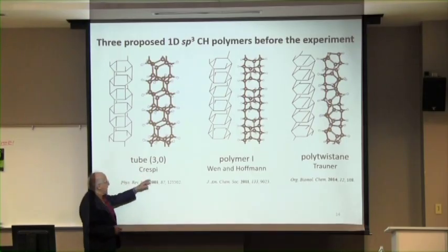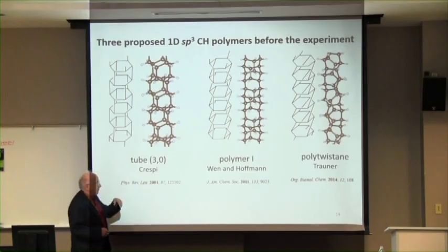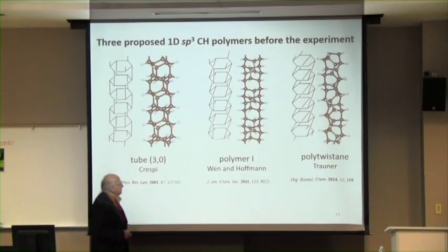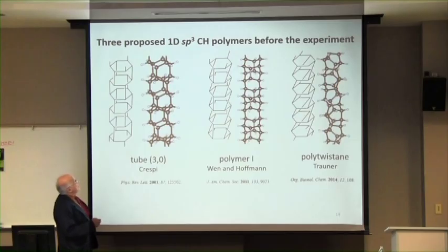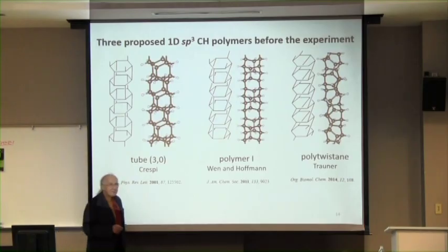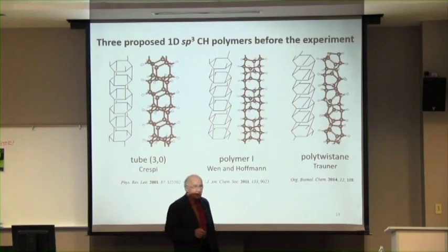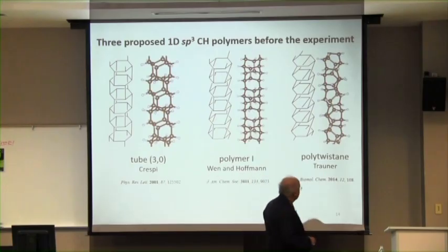Vin Crespi in 2001, in a paper we missed when we published on this 10 years later, suggested this structure, and here you see clearly for chemists the chair cyclohexane rings in this, with 3 axial positions up, 3 axial positions down. The price you pay for that arrangement, which is very nice, is eclipsing. This is a piece cut out from the hexagonal diamond structure and has both cyclohexane rings in it.